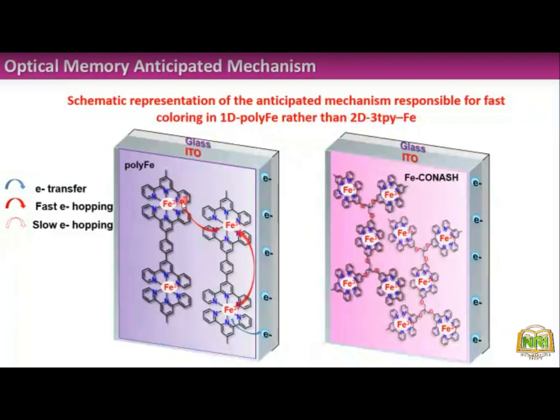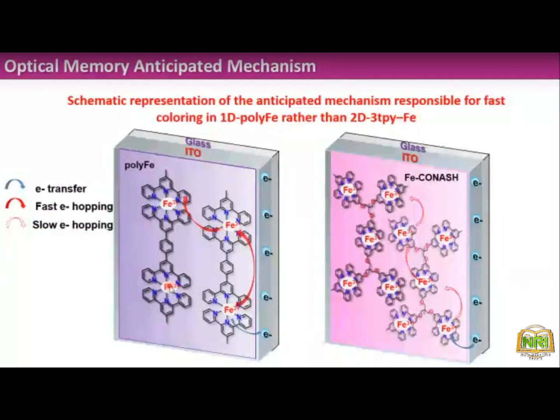But what's happening in our case is that, though electron transfer is okay, electron hopping is very slow from one center to another center. This is because we have a break, as it's a non-conjugated structure, so electron diffusion would be very low, and that is why our system is showing quite a high retention time compared to the previous conjugated ligand polymeric structures. Okay. So we can conclude that our compound is showing very good optical parameters, like good switching time and good coloration efficiency.